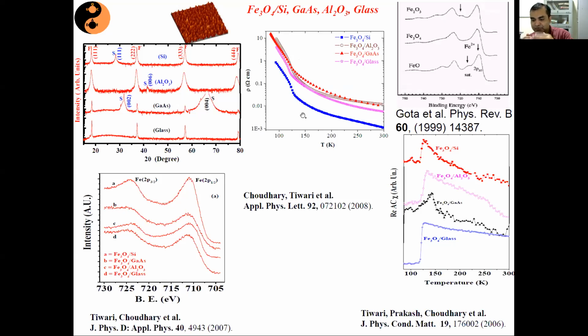Remember, when we picked the MgO substrate, the lattice parameter of 2 MgO matched with 1 unit cell of Fe3O4. But on these other substrates, there is a huge lattice mismatch between the film and the substrate. Therefore, in this case, the substrate direction does not control the film growth direction. Rather, it is the surface energy of the film material: the direction with the minimum number of dangling bonds has the minimum surface energy, and that controls the growth direction of the film. For Fe3O4, it happens to be along the 1-1-1 direction. So we have to understand that when we have a huge mismatch, it is the surface energy minimization which controls the film growth direction on a given substrate.